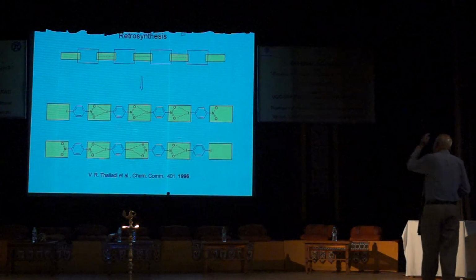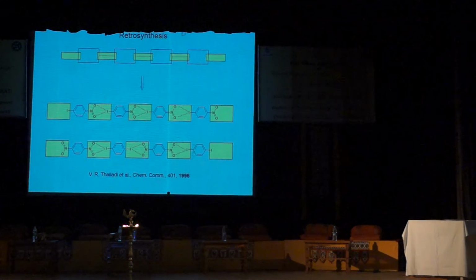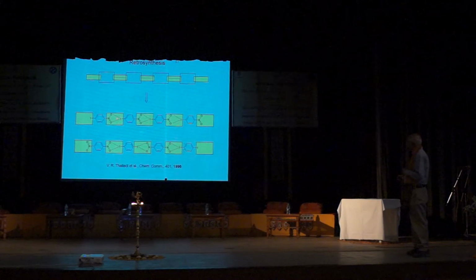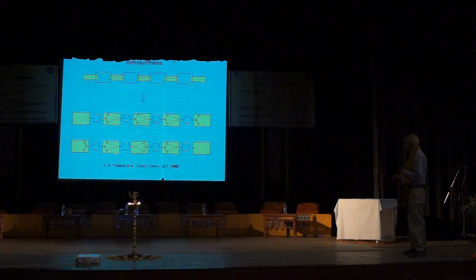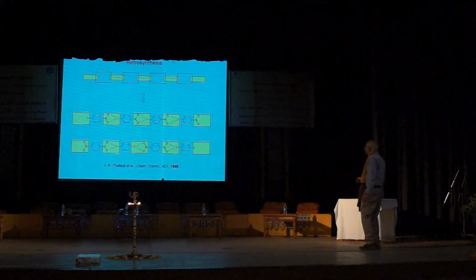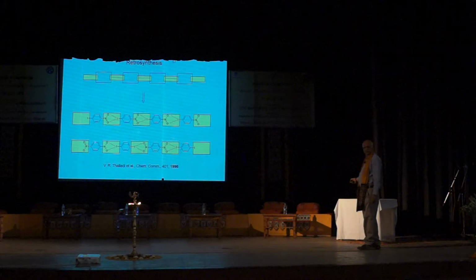Now look, we went back to some very early work which was done about 20 years ago. My group, where we identified actually at that time a totally new synthon, the iodo-nitro synthon, using the halogen bond, which is a iodonium here, I+. So this appeared to be coming up in a number of structures. Now look at this, this is the crystal structure of para-iodo-nitrobenzene, and yet the synthon is also found in the 1-to-1 molecular complex of 1,4-dinitrobenzene and 1,4-diiodobenzene.